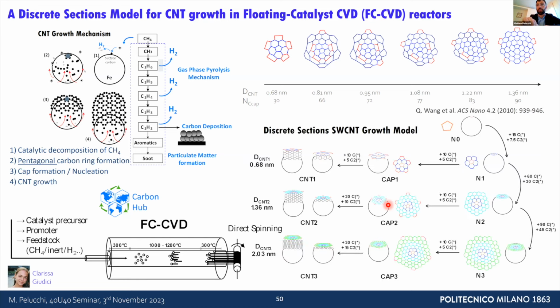So we can grow in many different ways, starting from the pentagon. We form this first N1 pseudospecies. This N1 pseudospecies, at one point, through the formation of a 5-member ring, will close on top of the catalyst particle like a table, and then the carbon attached to the catalyst will only be used to grow the nanotube in length.